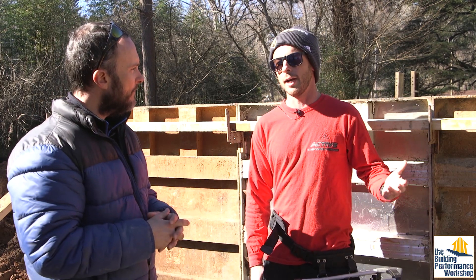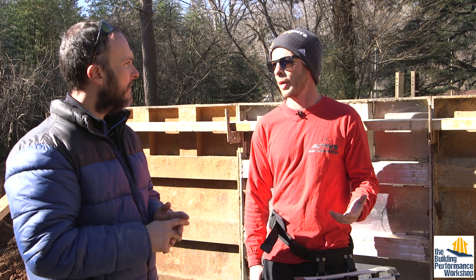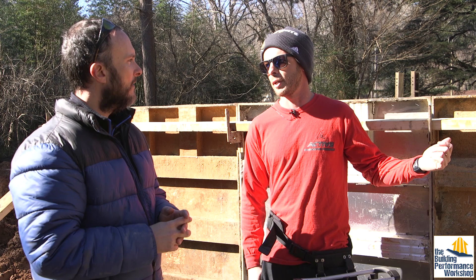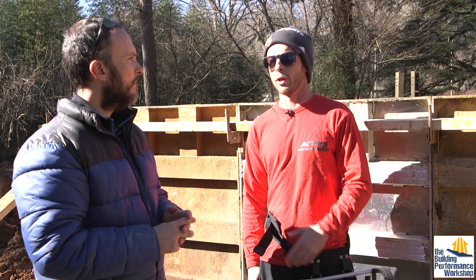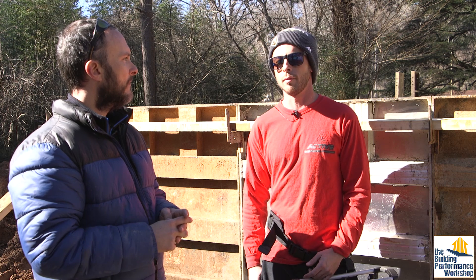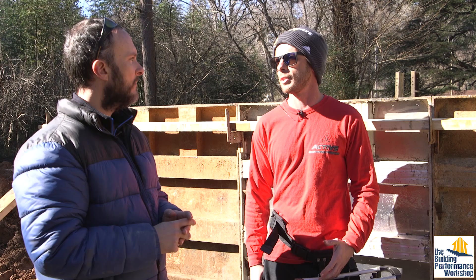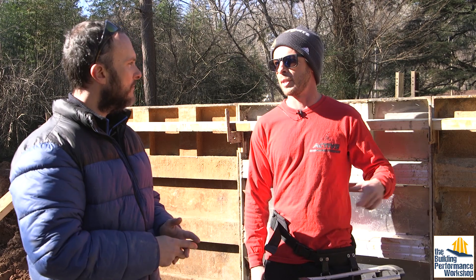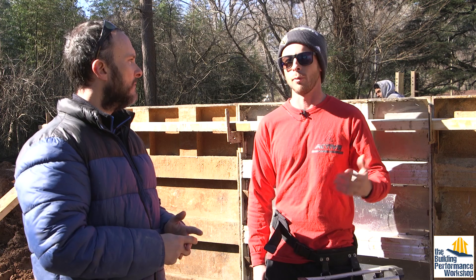The concrete will dry out. If he's got a 10-minute drive, it's not going to dry out as much. But if he's driving from across town — 45 minutes, especially with traffic here in Atlanta — the concrete left at a four-inch slump shows up at a two and a half or a three. So a lot of times we'll take a look at the concrete before we pump it out. And if I see it needs a little bit more water, I'll have them add, let's say, 10 gallons. So it goes from a four-inch slump to a five-inch slump. Ten gallons of the entire truck means you add an inch of slump, basically. We'll add 10 gallons of water and they'll mix it up, and once that's done, we have a higher slump because you added water to that concrete.